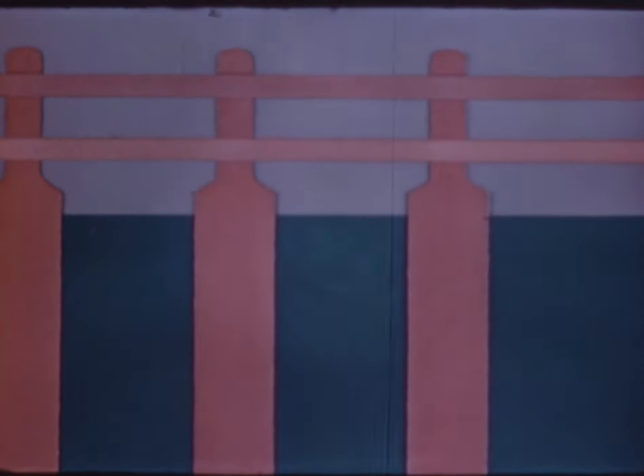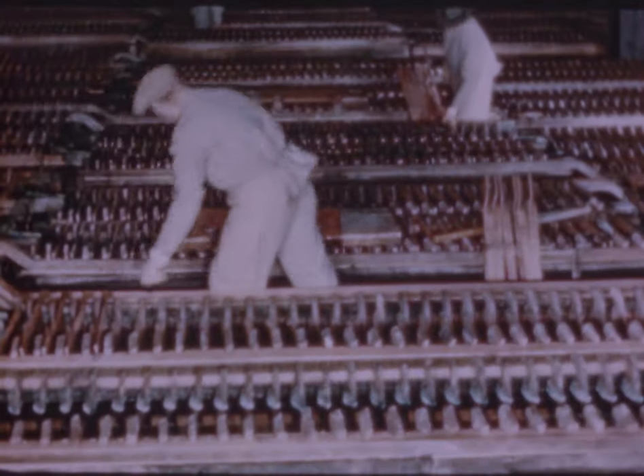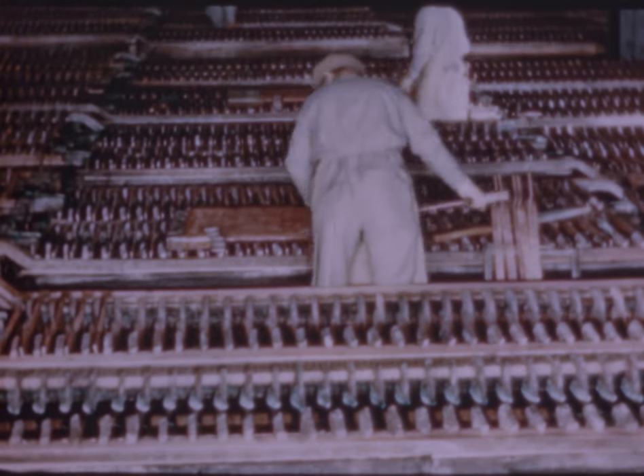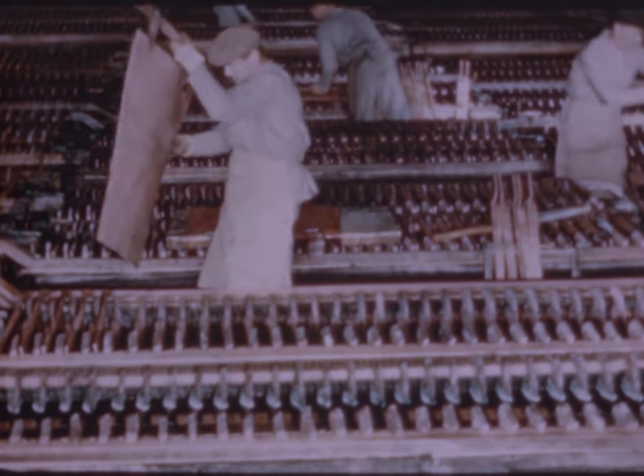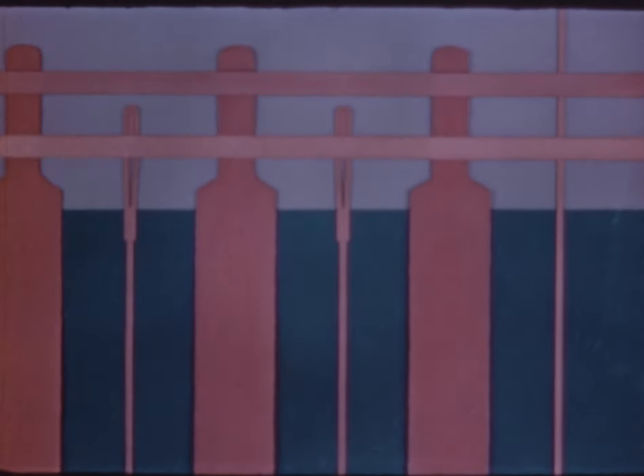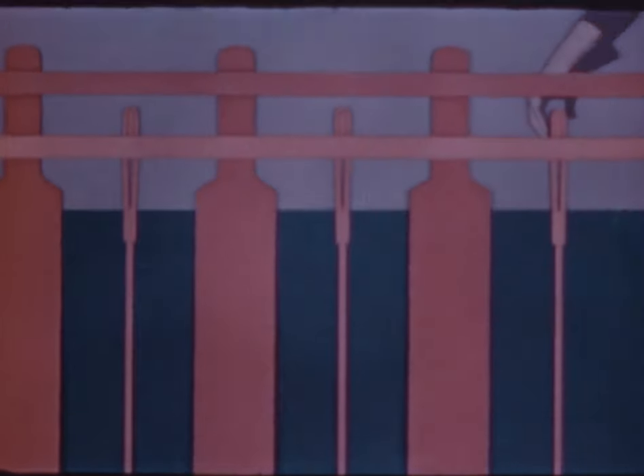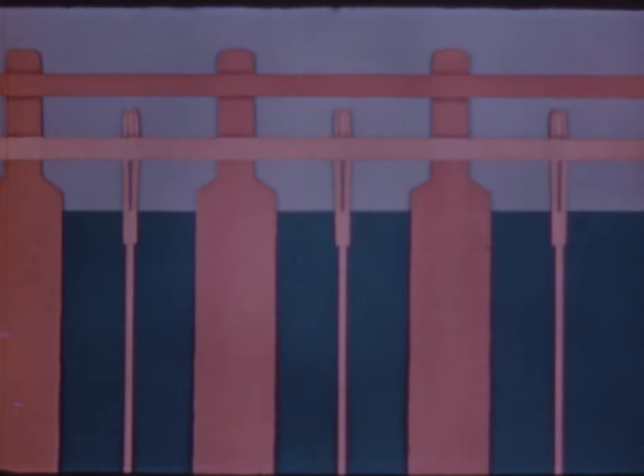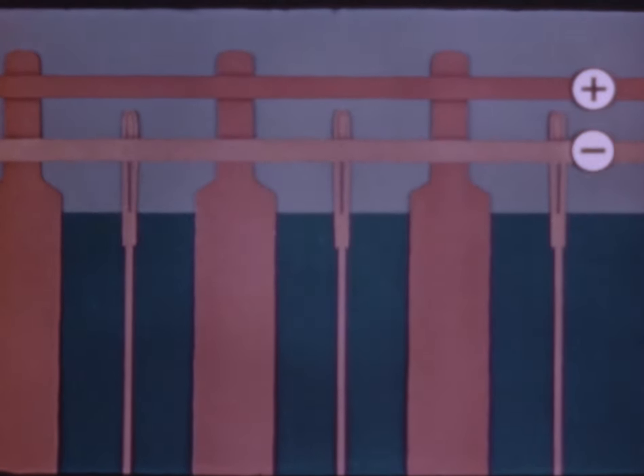Inside an electrolytic refining tank, 425-pound anodes are suspended in a solution of copper sulfate and sulfuric acid. Thin starting sheets of pure copper, called cathodes, are lowered into the tank between the anodes. Each tank holds 32 anodes and 33 cathodes alternately spaced. The anodes are connected to the positive side of a direct current circuit, while the cathodes are connected to the negative side.